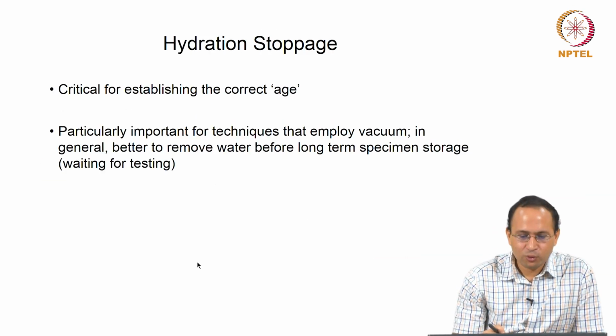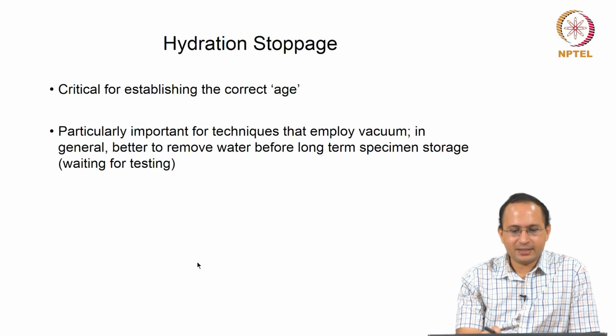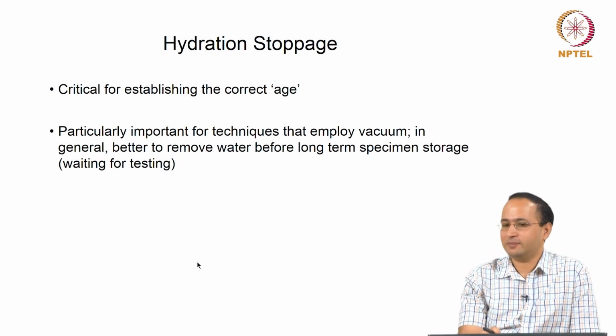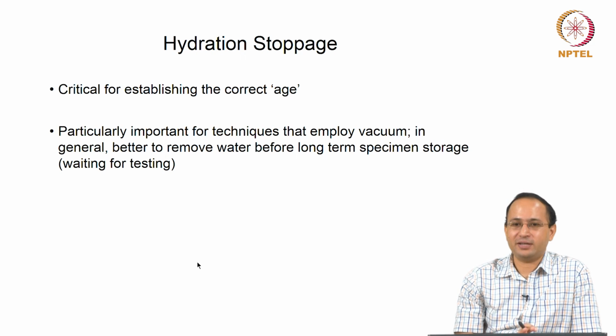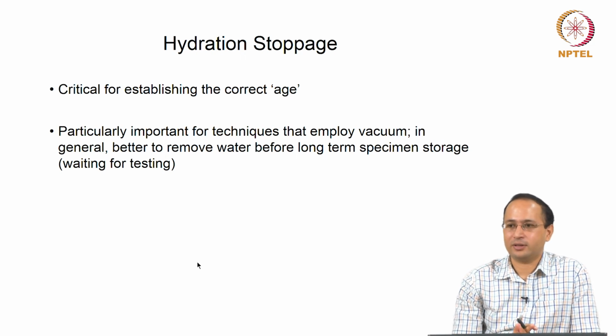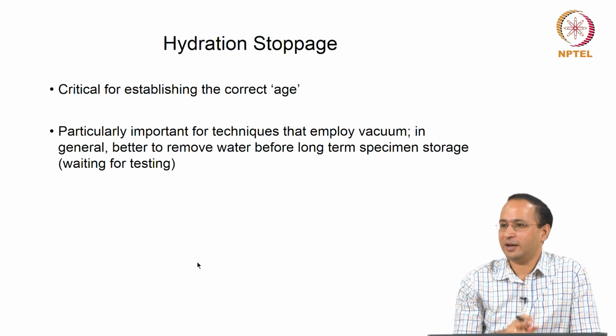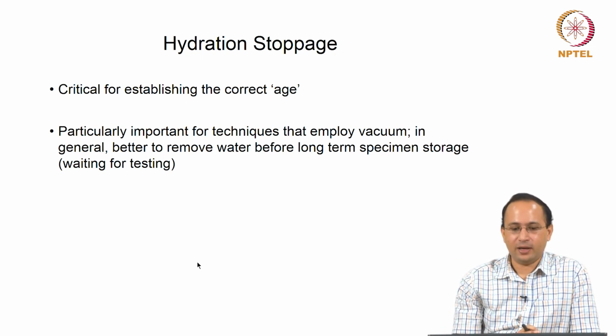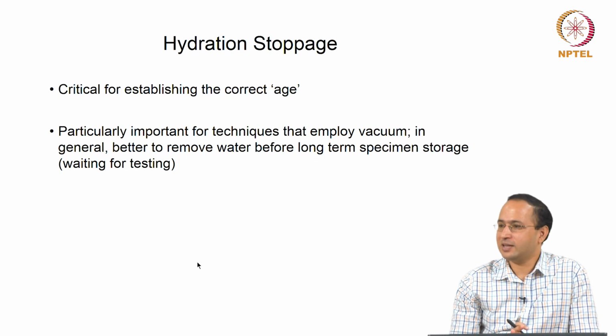Okay. One of the most critical steps is hydration stoppage, right. So why do we have to stop hydration? We are talking about cementitious materials. Basically we mix cement and water and let it hydrate, and during the hydration you have formation of calcium silicate hydrate. Cement hydrates continuously and gains strength, right. So why is it critical? It is critical for establishing the correct age, right.